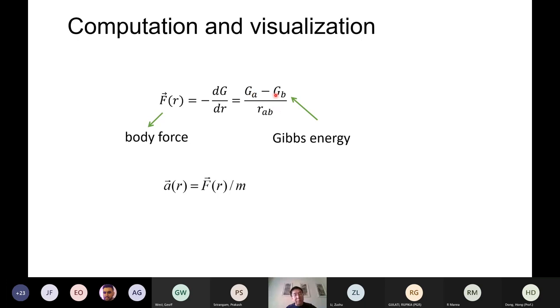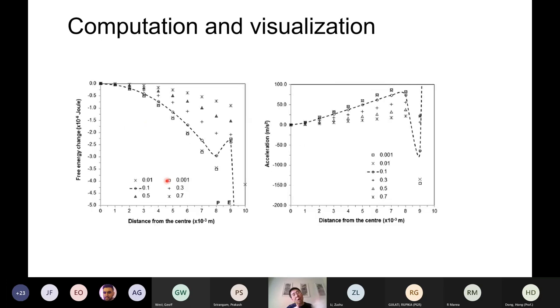So the free energy difference divided by the distance between the two positions gives the equivalent force. And then according to force, we can calculate acceleration. So if we calculate the free energy for the inclusion at different points, then we can calculate the force. So this is the free energy. When the inclusion is moved from the center to the surface, we see the free energy reducing consistently, reducing a lot, until it is very, very close to the surface. Okay, here is the surface, very close to the surface, and then it starts to pick up a bit.